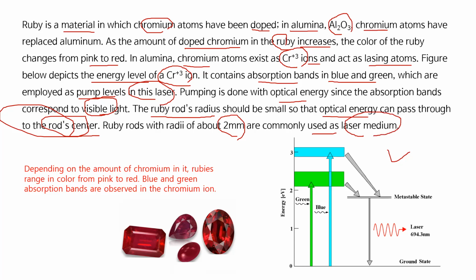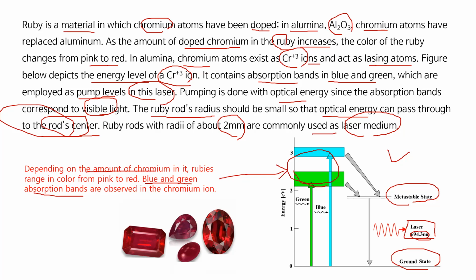This ruby laser is a 3-level laser. So this is a pumping level, and this is the metastable state and ground state. So the ruby laser is a 3-level laser. And the wavelength of laser light is red, whose wavelength is 694.3 nanometer. Depending on the amount of chromium in it, rubies range in color from pink to red. Blue and green absorption bands, these bands, are observed in the chromium ion.